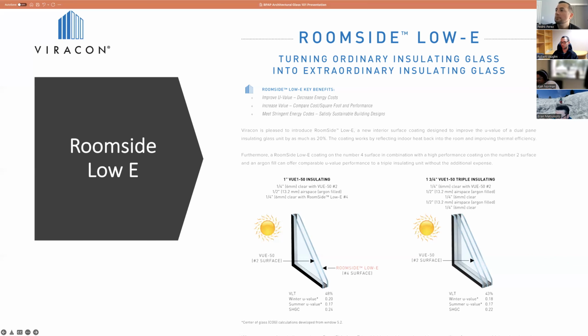This just kind of shows you, if you put the same coating on the number 2 surface, argon, and then a room side low E standard IG unit, compare the values to doing a triple IG with that same coating on the number 2, look at the SHGC. It's 0.24 versus 0.22. It's really quite close. The summer U value is the same. The winter U value is just 2 points off. But you also have a 5% higher light transmission. So it really can beef up the U factor performance of a unit. One thing to keep in mind is that it does not have the size capabilities that the rest of our products have. It is restricted to a 72 by 142. And it only is on a clear substrate. It's not available in a low iron substrate. So just something to keep in mind.